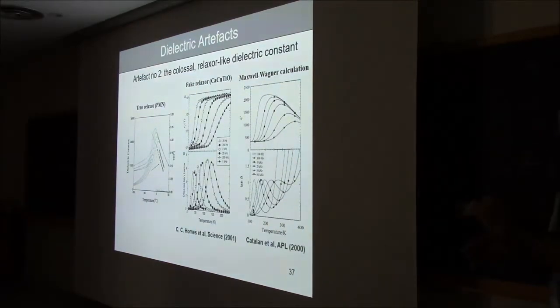Basically, it happens faster than the electronics. The switching speed is limited by the speed at which you can provide charge to your ferroelectric. But yeah, if you go to very low temperatures, there's an exponential, an Arrhenius law, and because it's exponential, it can get slow very rapidly. So at low temperature, ferroelectrics can become unswitchable, basically because things are happening so slowly. The intrinsic coercive field is very, very large, so you need to rely on domain movement, and if the domain walls are frozen, then you won't be able to switch. Okay. But for the sake of practical applications, room temperature, microseconds. Yes? Okay.